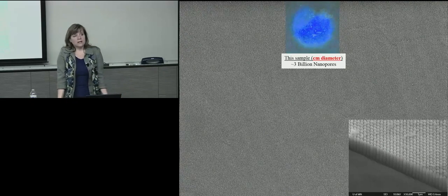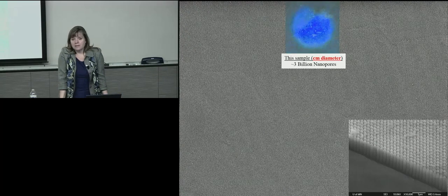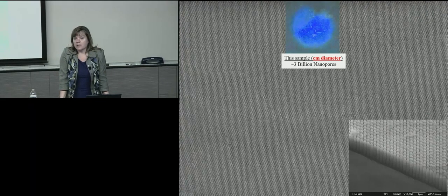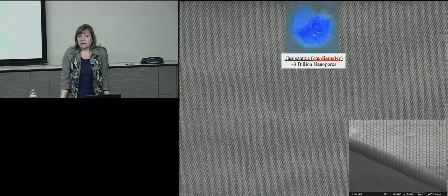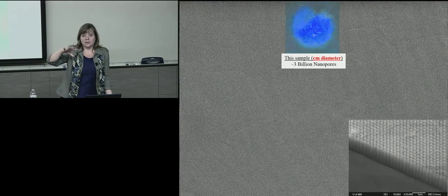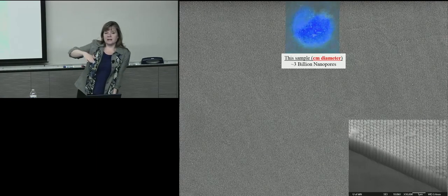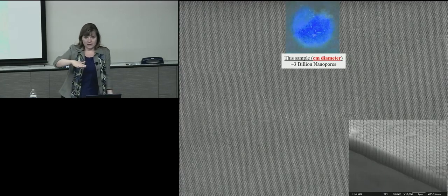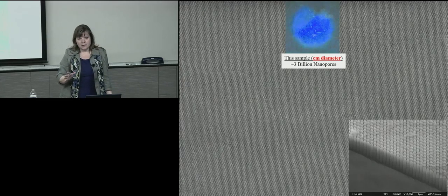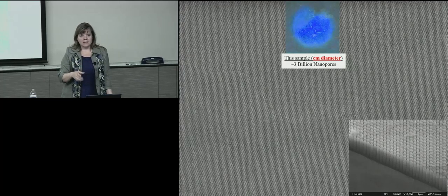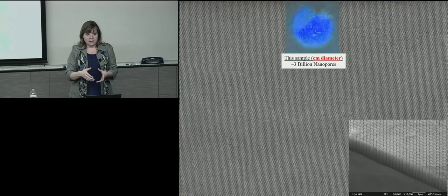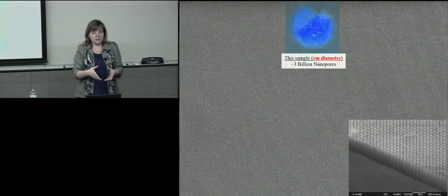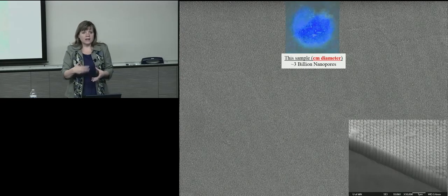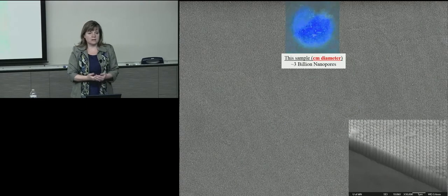Each stamp, we have used them like 20 or so times, and we kind of end up switching to a new parameter at that point. We anticipate we could use each stamp 100 times. I should also mention it depends a lot on how you're pressing. So if you use a nano imprinter that has a regulated printing, which there are a lot of these in industry, and also Seagate does have, they have made 20 nanometer dimples over an entire, I think it was a 4-inch wafer. So you can do it by different lithography means than we have available.